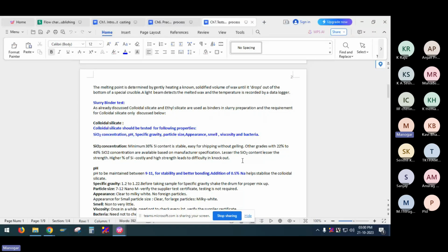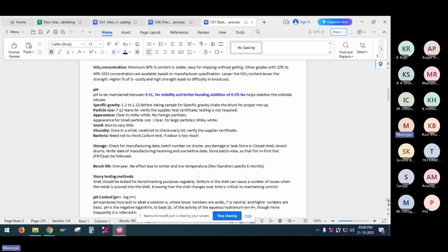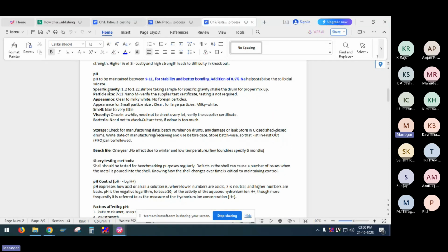Lesser the SiO2 content, lesser the strength. Higher the SiO2 content, it is costly and also the strength is more. When the strength is higher, it is difficult to knock out. Then pH. The pH for the SiO2, the sodium silicate, should be within 9 to 11. That is for stability and better bonding properties.